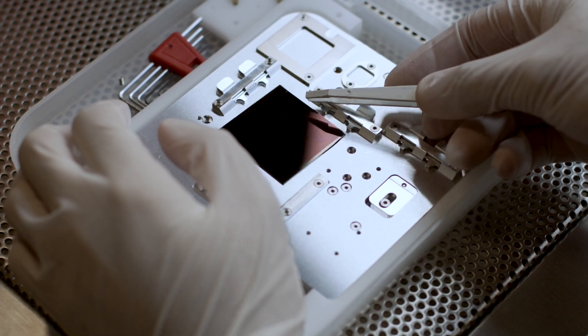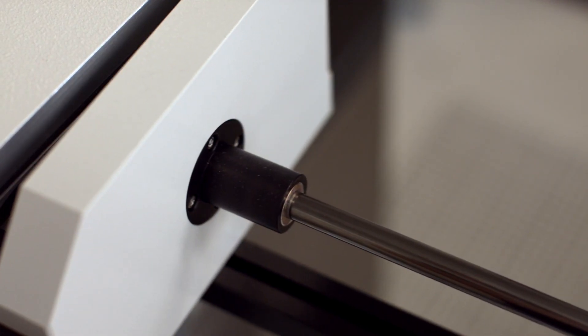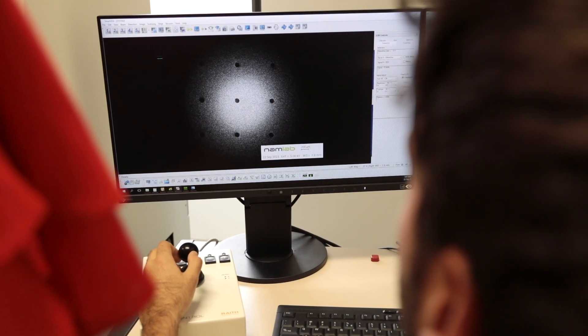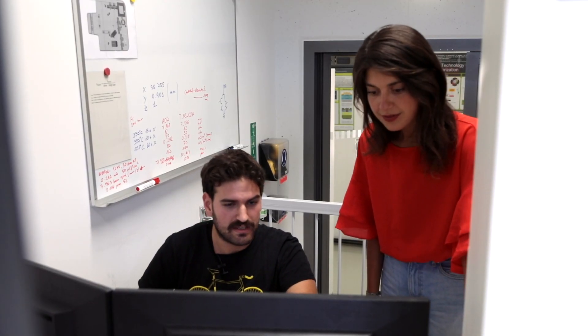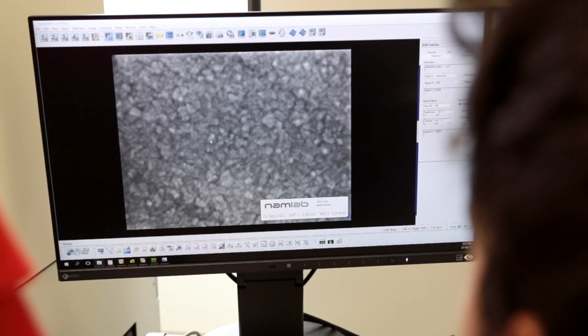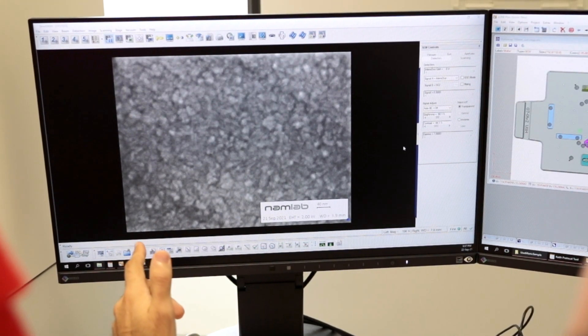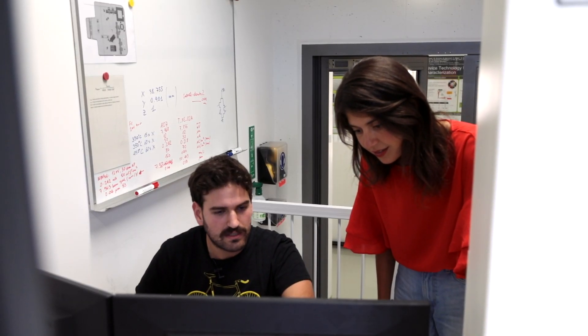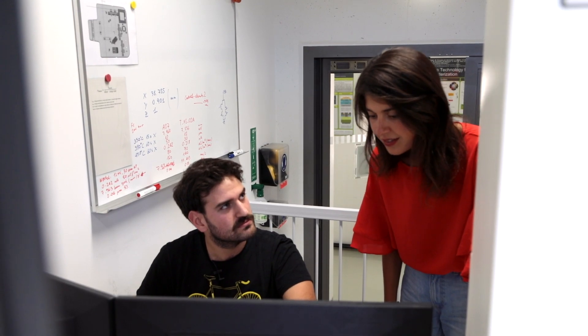Microscopes are one way to look at the final sample. These are the top electrodes that were deposited — they are more or less the size of a human hair. And if we further zoom in, here you can see the ferroelectric layer. Here you see the grains. They are more or less 20 to 40 nanometers wide, which is more or less 100 atoms in a row.